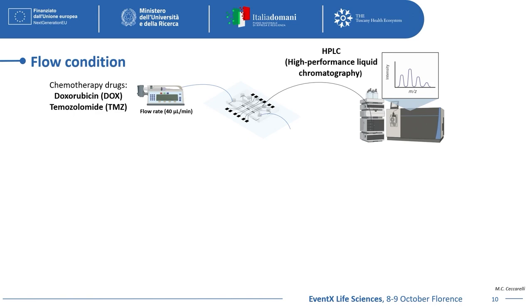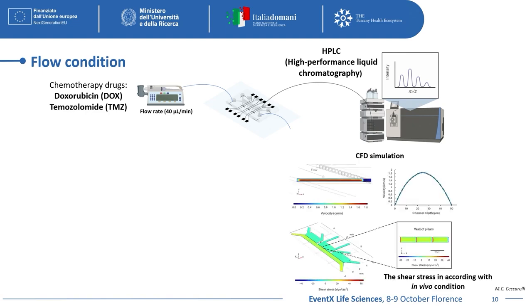Once we characterized the device, we also tried to induce flow conditions inside it and to induce the shear stress in order to mimic the in vivo situation. We performed a simulation to identify the flow rate, based on the geometry and the design of the device.